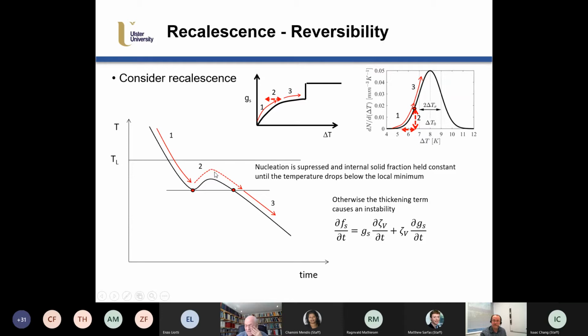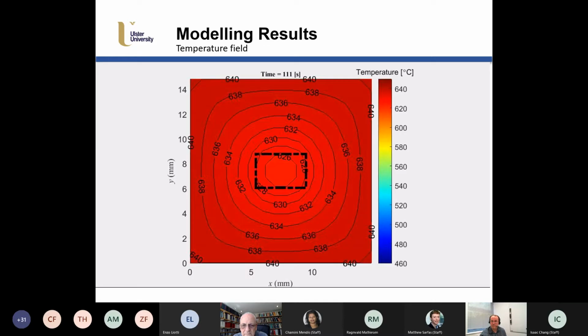The upshot of this is that if we didn't do this, then the model would become oscillatory and unstable. And so this was something we pondered and something we looked at, and we think it's quite physical and quite realistic, and it would be worthy of further investigation, especially this point on the thinning of equiaxed within the envelope under recalescence. But we think this worked well.